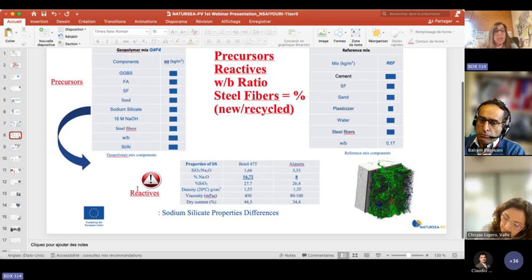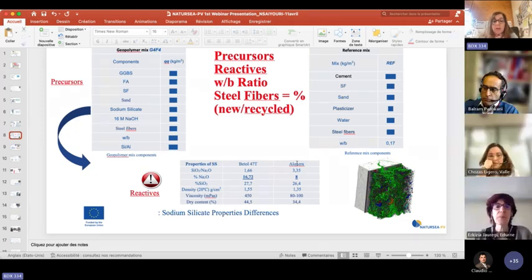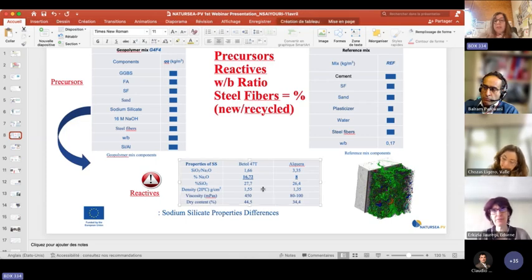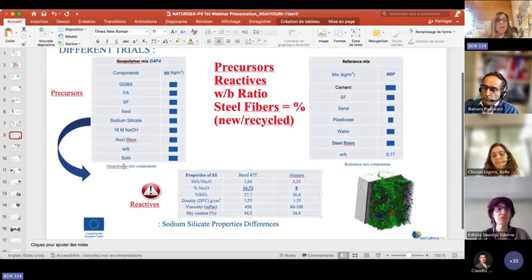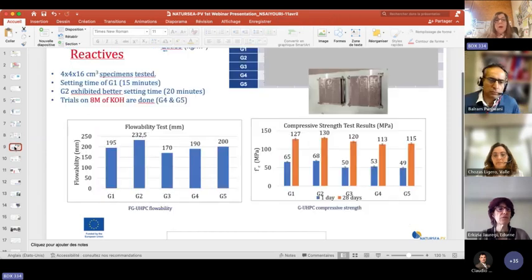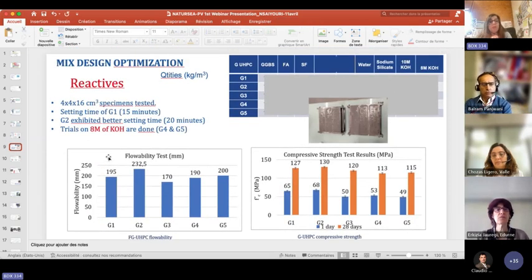One important point here: we can see that reactives, like sodium silicate here, depend on the supplier, or where you buy it, because composition can be very different, and you can have different results with different kinds of sodium silicate. It's not something standard that you can buy and work with. It can be different from one supplier to another. So we tested many of them, with different precursors. I go to the change of reactive, and I stay on this point.